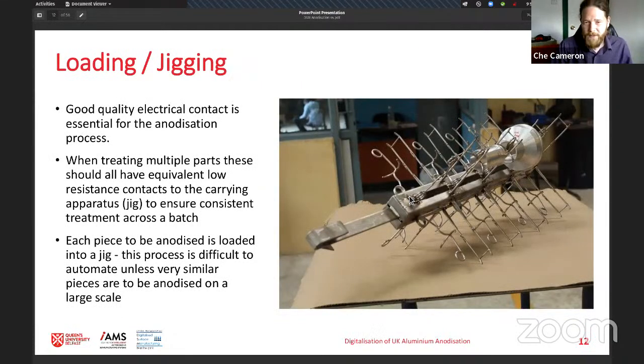After you have those relatively clean parts at their final finish, they go into jigs for anodization, and that's just a way to hold the part that makes an electrical contact to it. As the parts are loaded in, they must have a good low resistance contact to this jig, and it's a process that can be very difficult to automate. The picture here is quite a simple jig, but if you're using different shapes of parts, different shapes of jigs, it is very resistant to economical automation.